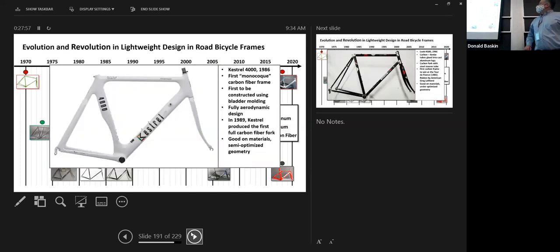It wasn't until about 1986 that Kestrel came out with a true monocoque frame. At least they call it a monocoque. I would call it semi-monocoque or a mid-spectrum design, where they made this whole frame in one mold. So they got female molds, okay, and then they have like a mandrel of some sort that expands under heat or under pressure. So sometimes they'll use like a silicone mandrel to lay the carbon fiber over, and then they put the carbon fiber prepreg on there, which is carbon fiber and epoxy kind of already mixed together in a sheet, sticky, so you can get things to stick together, right?